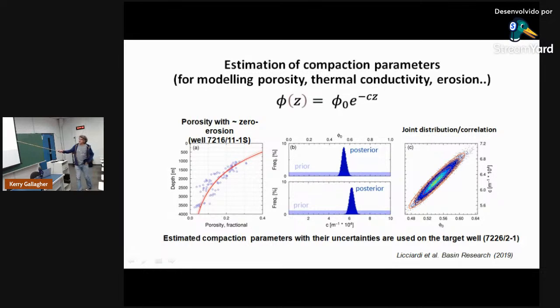So here's this well with some data. The well that was to the left, where I said there wasn't much erosion. So this is our reference curve in this part of the world for porosity changing with depth. And so we estimated these parameters, the phi 0 and the C, using Markov chain Monte Carlo. And just to show how that does, this was our prior, say for the surface porosity, between 0 and 100%. And this is the compaction coefficient C. So we said the values can be anywhere in these light blue bands. And when we calibrate against the data, this is what we get for the posterior. So we learn a lot about the good values for those 2 parameters.